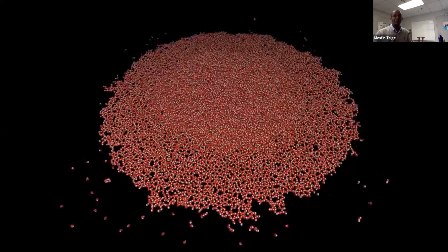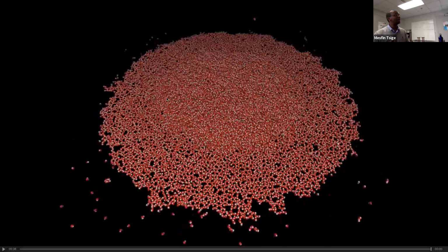In the case of water spreading on this surface, what we have seen is just a monolayer. Others think that maybe another layer may develop over time. In the droplets that we have investigated, we didn't see multiple layers coming out. We have only seen single layers, and we have done that for different droplet sizes. And of course, in our case, we wanted to characterize the hemispherical cap sitting on top of the monolayer.